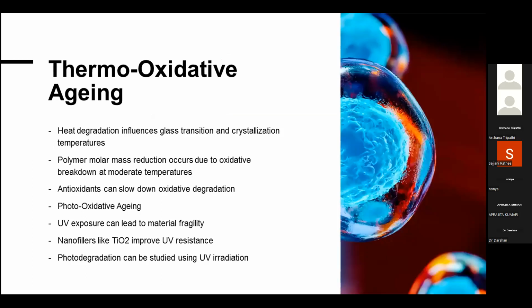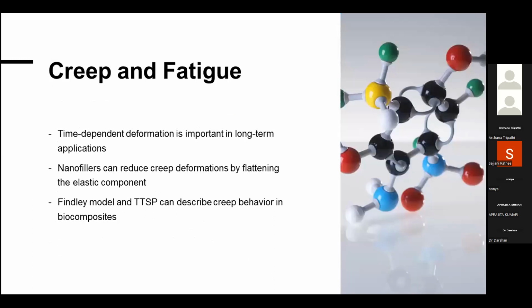Thermooxidative aging: heat degradation influences glass transition and crystallization temperature, and polymer molar mass reduction occurs due to oxidative breakdown at moderate temperature. Antioxidants can slow down the oxidative degradation. Photooxidative aging: with UV exposure, nanofiller like TiO2 can improve UV resistance. Photodegradation can be studied using UV radiation.